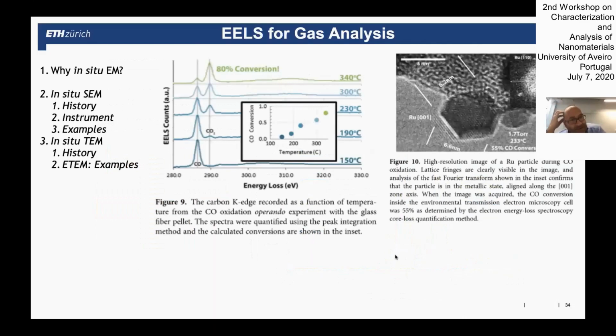Again, like in many cases, you have this integral measurement of the gas phase composition. So, for example, you start with CO at low temperature, and as you heat up in oxygen and CO, you see that CO starts to get oxidized to CO2, and at a certain temperature you have already a lot of formation of CO2. That is integral. That's what you measure with the beam passing through the vacuum, through the hole. And at the same time, of course, you can also image some particles. And that is very beautiful because you can then correlate catalytic activity with something that might happen to the particles when they are in this gas phase.